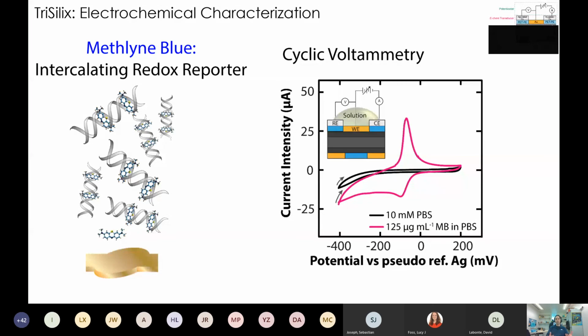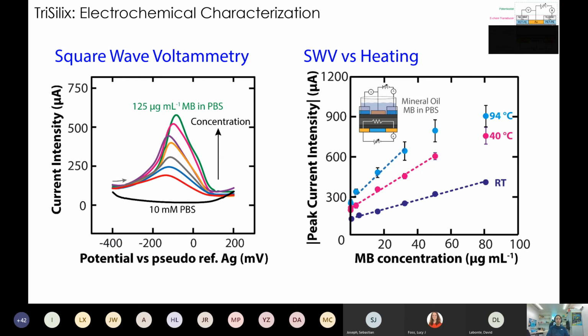we will have less of the signal. And we have done some characterization to show that our electrodes work really well, and they're sensitive for detecting low amounts of the reporter molecule, which is the molecule that interacts with the DNA, which would allow us to detect low amounts of DNA in solution. Another interesting thing is that because we have a heater, we can change the temperature at which we perform the detection itself. And it turns out that as we increase the temperature, our device becomes more sensitive because the reporter that we detect can diffuse onto the electrodes a lot faster.